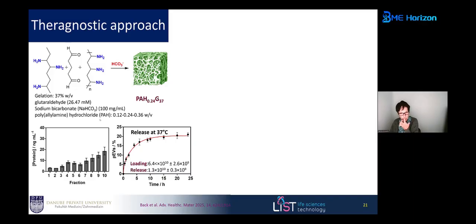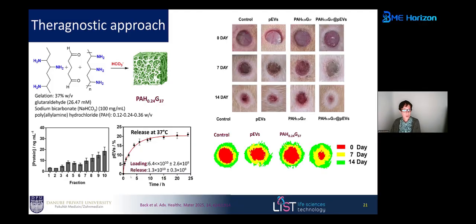Because you have sodium bicarbonate at a certain pH, you will generate CO2. And these CO2 bubbles can get impregnated in the gel, so you actually get a foam. In this foam you now have a very high surface area. So what we did here, we integrated proteins, actually blood-derived extracellular particles, which have been shown to be really adapted for wound healing. So we can load these gels, we can release them, and then we can look at wound healing effects. I don't want to go too much into details here, but these were the rats.